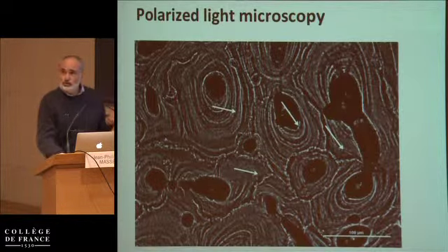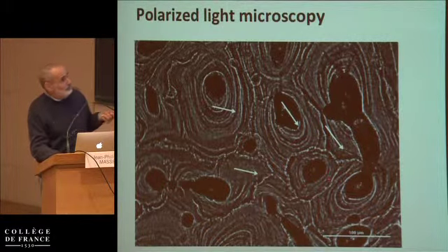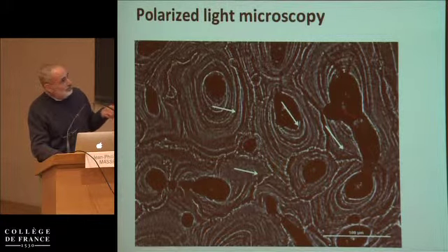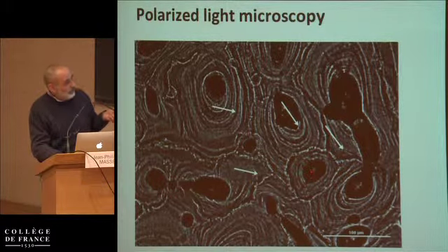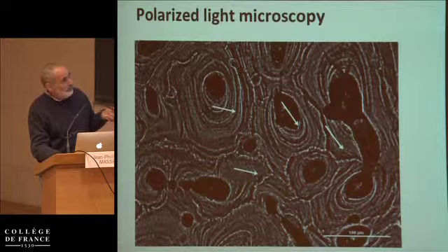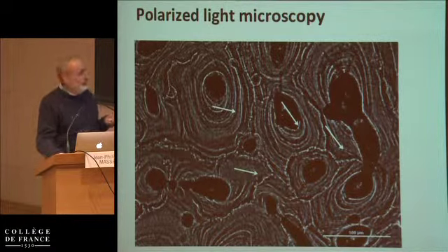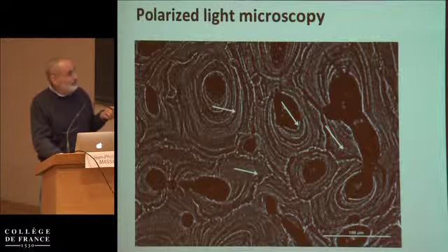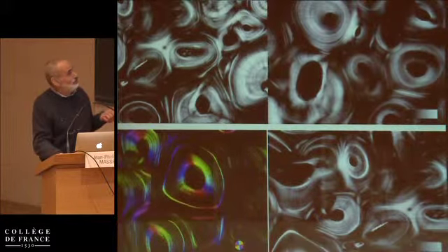We took this to polarized microscopy, and I think this is pretty much a clincher for me because, again, this is a blue marlin, the bill of a blue marlin, and you can actually see what really looks like an osteon with lamella, a central canal, and this osteon definitely eats into this one and probably also into this one, and we have many images like this. So I realize this is not proof that they remodel, but it's suggestive. This is just a pretty image of the same, so I'm not going to spend much time on this.